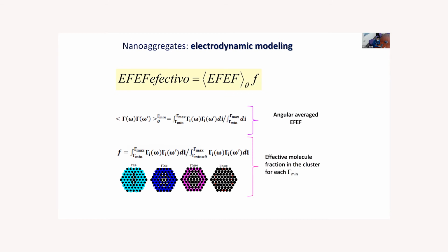Well, we rationalized these results, making a lot of calculations and taking into account the enhancement, in which place of the cluster is the best place to enhance the signal of the molecules. And we found that in the case of very big clusters, only this region was a very good enhancer. Then all the hot spots in the middle of the cluster were not enhancing because the electric field was very low.